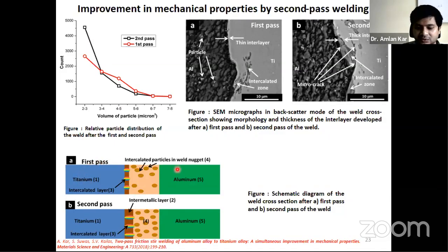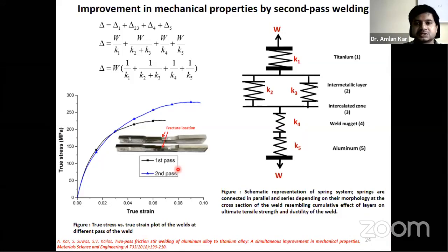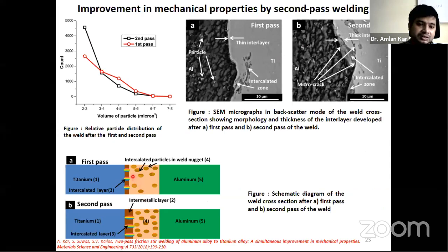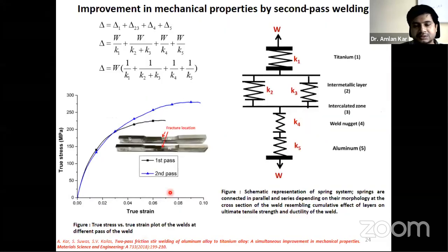Based on the microstructure, we have correlated the microstructure to the spring model, because in this case you can see that at the interface you have the intercalated as well as the intermetallic layer. So these two are actually connected in parallel, but the other different zones are connected perpendicular, or in series. Similarly, we have developed a model, and we have seen that this model correlates very well to the stress strain behavior of the materials.